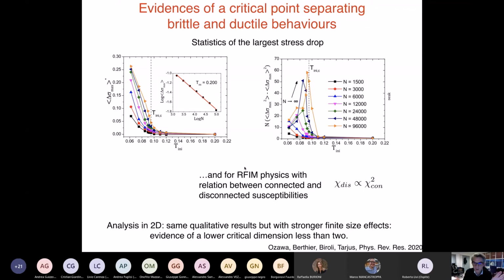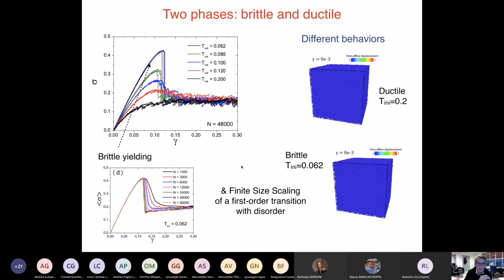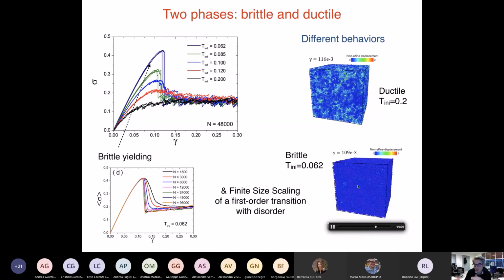All right, if you remember what I told you about the random field Ising model, there are different features of the spinodal. There are 2 different phases, there is a critical point, and then there is the physics related to the discontinuous yielding, the yielding that you see here. In the case of the random field Ising model, the physics was related to the existence of rare seeds from which the failures start. And what we see here is that this discontinuous jump is related to the existence of what we call a shear band. So a failure which is localized, in 3 dimensions, on a 2-dimensional part of the system. In 2 dimensions it will be on a line.